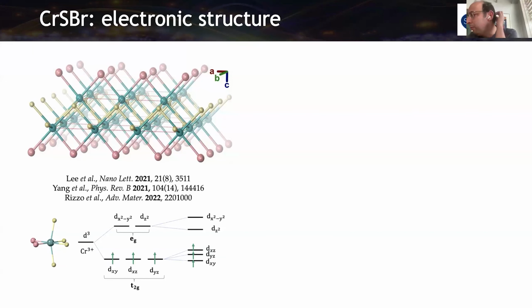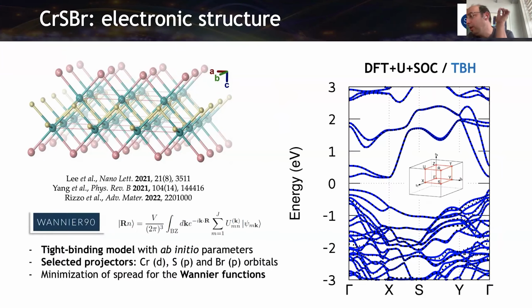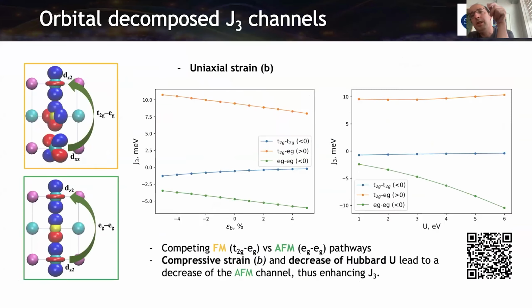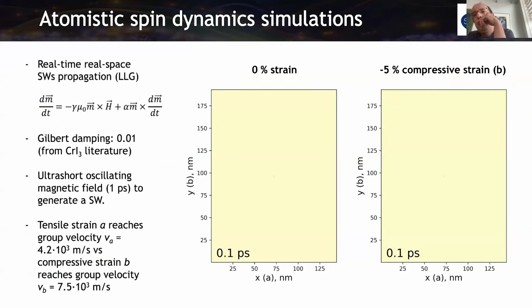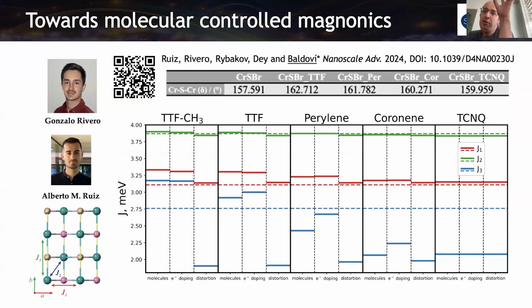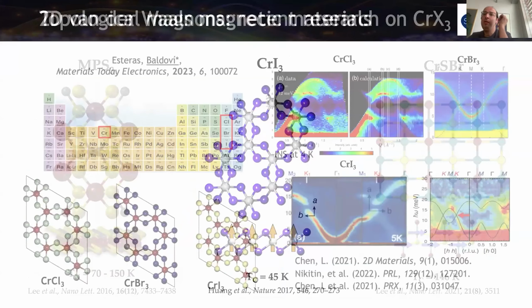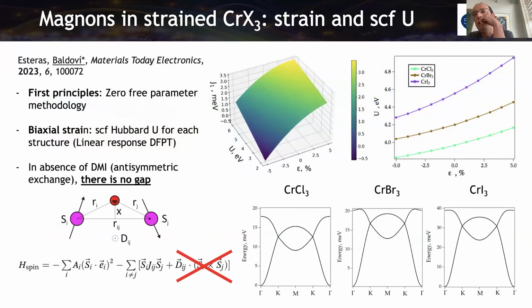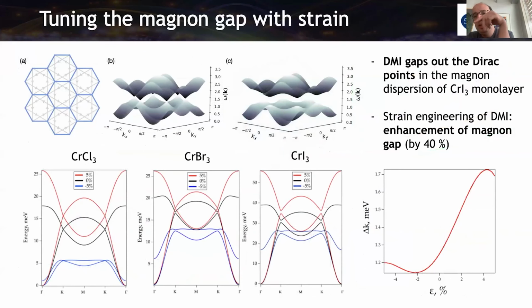In one slide you showed the gap in the chromium iodide at the K point, and then you showed that by strain you can close the gap. I remember there was some discussion about the value of this gap, that DFT couldn't reproduce the experimental gap. I'm wondering, here, how large is this gap at the K point that you found? Yeah, it's very, very small. I don't remember exactly the amount, but it's like 5 or 6 meV, I think.